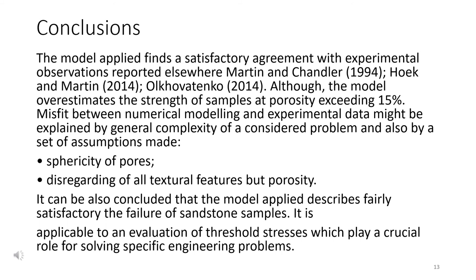Although the model overestimates the strength of samples at porosity exceeding 15%, the misfit between numerical modeling and experimental data may be explained by the general complexity of the problem and the set of assumptions made, including sphericity of pores and disregarding of all textural features but porosity. It can be concluded that the model describes fairly satisfactorily the failure of sandstone samples and is applicable to the evaluation of threshold stresses, which play a crucial role in solving specific engineering problems.